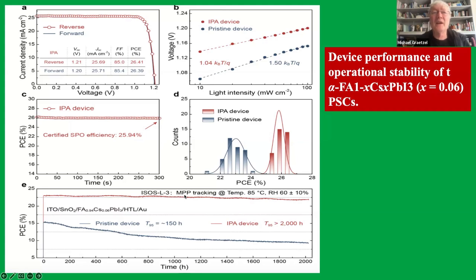So there's always a voltage that gives you the maximum power output, the maximum efficiency, if you like. And you can see that just by using that simple trick with the acetate, he now gets a result of over 2,000 hours of full light soaking, with humidity and the maximum power point. So it's high temperature, full light, and maximum power, and the electric field is there. And still you can see there's hardly any degradation. Now, if we take that result and ask, can I extrapolate? Yes, you can, and a result like that is comforting. It tells you that this cell would have an extrapolated lifetime of over 20 years.